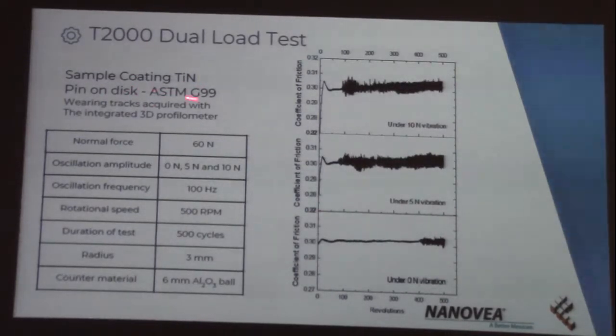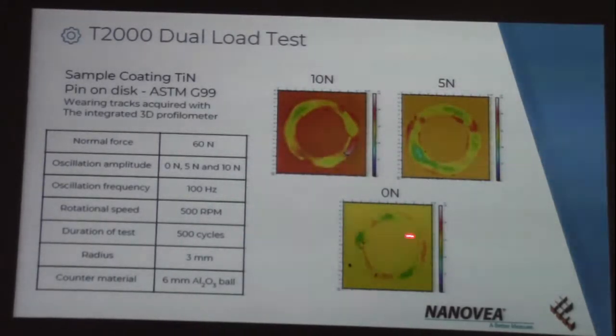In this case it is a thin coating, and we can see under 0 vibration the same plateau, and then severe fatigue occurs when we reach the substrate, and in this case under 5 Newton and 10 Newtons the behavior is the same. So we can understand that without superimposed vibration we have one kind of behavior in the material. Then if we have a vibration, the behavior is similar, even if the final result can be different, but we can clearly see a different behavior with vibration and without vibration, that until now it was not possible to see with this kind of test. And these are the results with the 3D reconstruction.